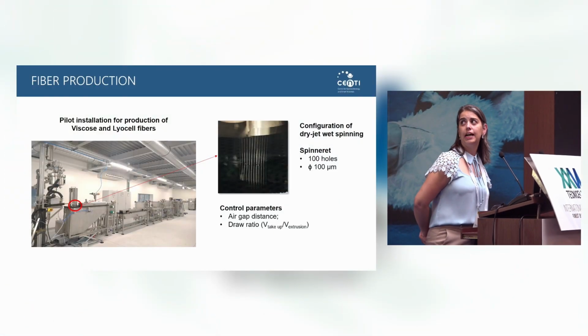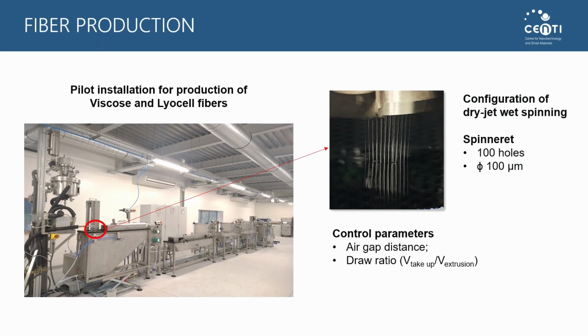This spinneret has 100 holes with 100 microns in diameter, and the main control parameters were air gap distance and also the draw ratio, that is the ratio of the speed of the first godet and the extrusion speed.